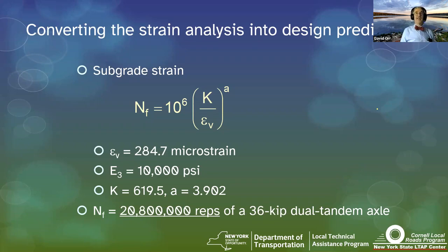And here's what's cool about it. When it first came out, everybody says, ooh, it's fancy. It's scientific. It's European. The idea is to get stiffer as you get towards the surface, with the stiffest layer at the top, and the thicknesses are such that the cracking occurs at the surface. Let's describe a pavement that would meet that criteria.